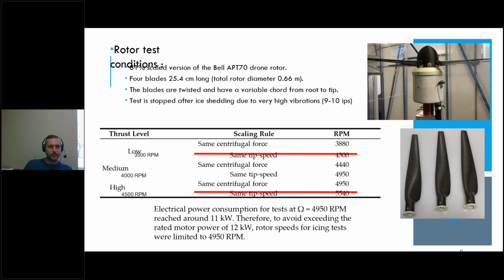For the rotor test conditions, we went with an 81% scaled down version of the APT-70 drone rotor. So 4 blades of 25 centimeter long for a total rotor diameter of 66 centimeters. And we decided to test 3 different thrust levels, so low, medium, and high thrust. So for the scaling rule, we went with 2 different scaling calculations. So the same centrifugal force and same tip speed. So for each thrust level, we had 2 corresponding RPMs for a scaled down version of the rotor.